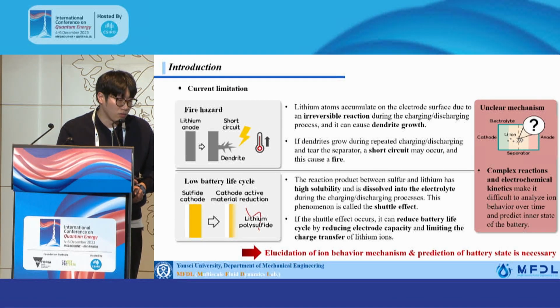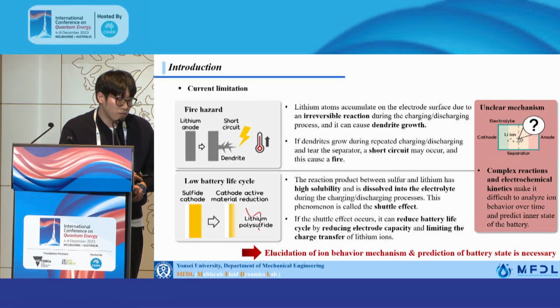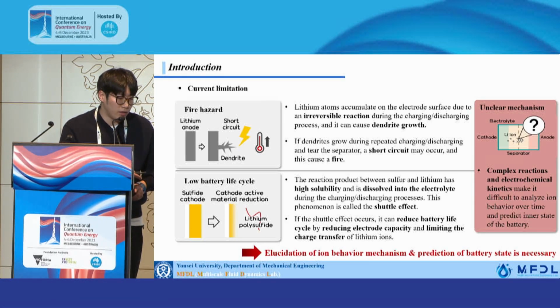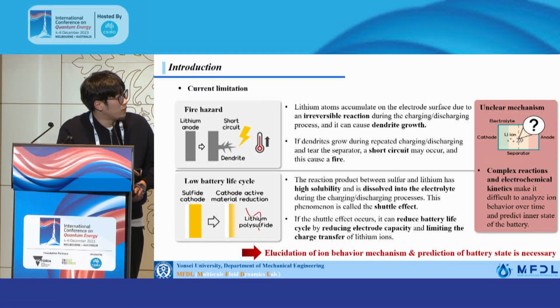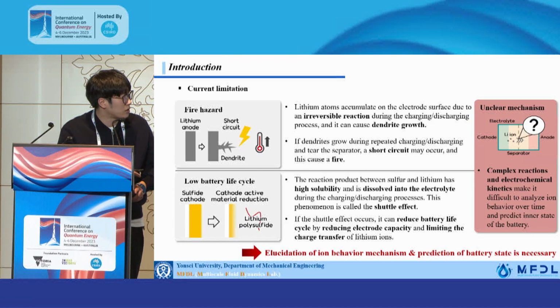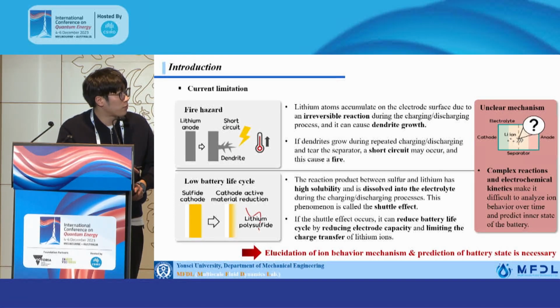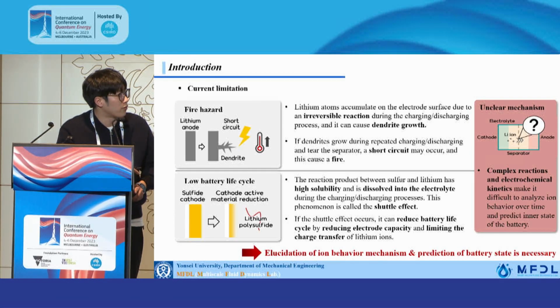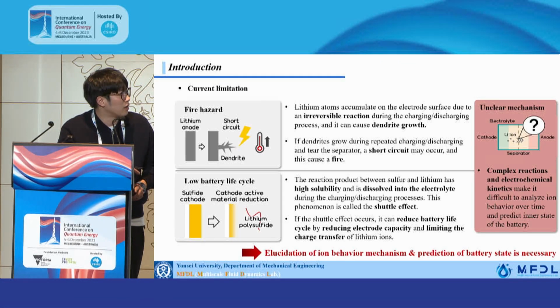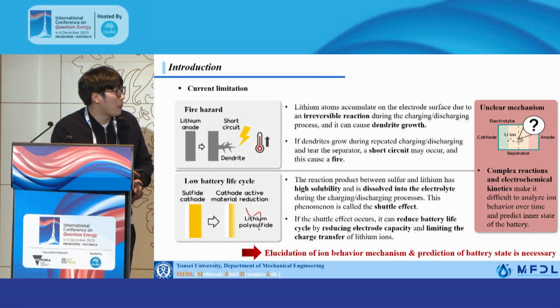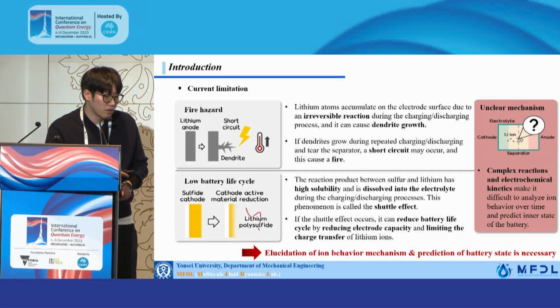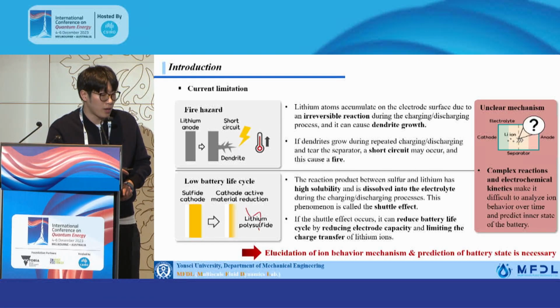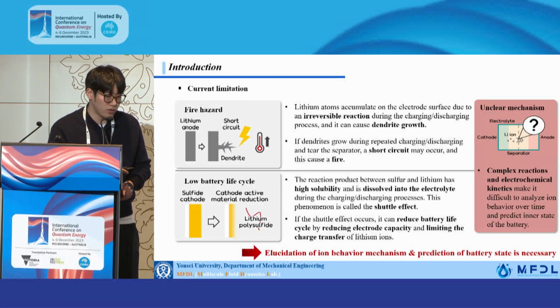The second limitation is the low battery life cycle. In the lithium-sulfur battery, the reaction product between the sulfur and lithium has high solubility, and it is dissolved into the electrolyte during the charging and discharging process. And this phenomenon is called the Shuttle effect. If the Shuttle effect occurs, it can reduce the battery life cycle by reducing electrode capacity and limiting the charge transfer of lithium ions. And both of these important phenomena have complex reactions and electrochemical kinetics, so it is hard to analyze the ion behavior over time and predict the inner state of the battery.